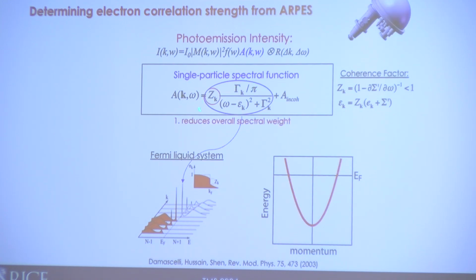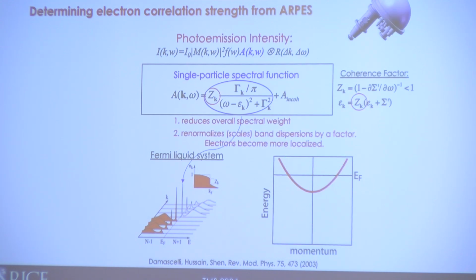First of all, you notice that this is the overall spectral weight modulation here. So essentially, if you have correlation, you will see a suppression of your spectral weight. And then the second part where this enters is here. It modifies the dispersion relationships that we actually observe from ARPES. And essentially, you will see that there's an overall squeezing in energy of these bands. So both these ways can be utilized to gauge the strength of electron correlation effects seen by photoemission. And of course, if you keep going to the Mott limit, you get zero spectral weight with a completely flat band, and that's the Mott limit.